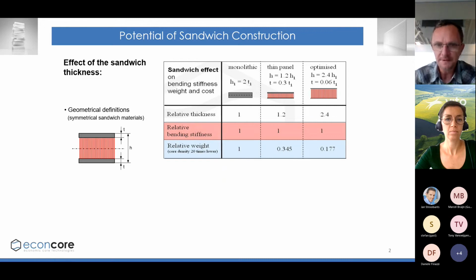So let me start with this slide that explains a little bit what a sandwich panel is. And sandwich panel is what EconCore is about pretty much. Here we have an example of a monolithic panel with certain thickness, certain stiffness, certain weight. Now, using exactly the same material type, one can build a sandwich panel with relatively thin skin layers with a low density core in between. And thanks to the sandwich effect, with just a small increase in thickness, one can target the same bending rigidity at much lower weight compared to this monolithic material.